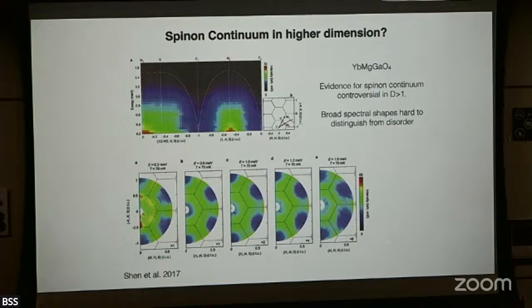The problem is that in the system, magnesium and gallium have about the same ionic size, and they substitute for each other, basically at almost the complete utter substitution, which incredibly disorders the crystal field environment for ytterbium. And so this system is just disordered like heck. And it turns out to be a rather unfortunate repeating theme in the field of searches for quantum spin liquids, is that systems that we're interested in, which may be good candidates for this interesting physics, turn out to have other problems which allow us not to understand what's going on.